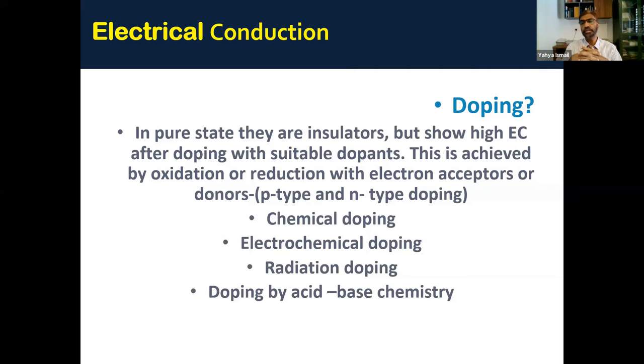For example, if I take polyaniline, you have a long chain of polyaniline with extended pi electron conjugation. When you dope it with some protonic acid, H plus ions are doped. Once it is doped, there is a soliton. The solitons in conducting polymers, in polyaniline, are referred to as polarons. It's an electron trapped in a lattice polarization. When you apply potential, the polarization along with the quasi-particle polaron will move in the direction of the electric field and then conduct electricity. This is the simple acid-base chemistry.